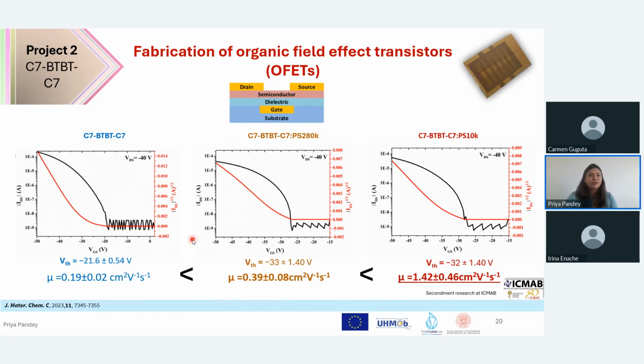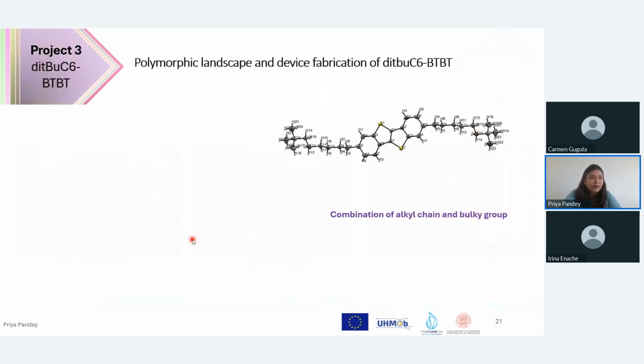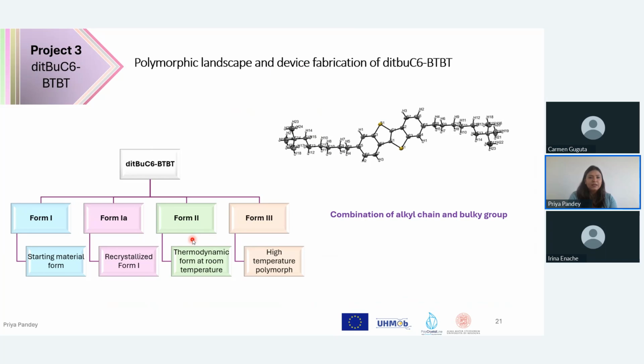And finally, I would like to talk about one of the other interesting molecules from my point of view. Again it has a similar chain length, but this time it has a 6-carbon alkyl chain, which is capped with a tert-butyl bulky group. And exploring the polymorphism, I found that it has 4 different polymorphs. Basically, it can be confusing here why there is form 1 and why there is form 1A. Form 1 is the starting material, which is obvious, but form 1A is recrystallized form 1. Let me explain why it's written like that.